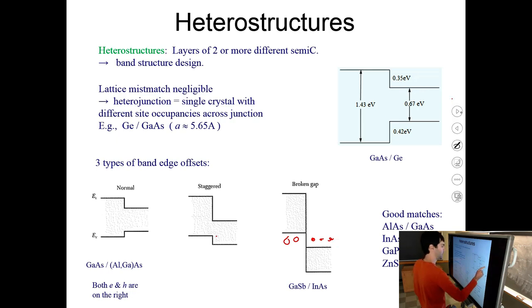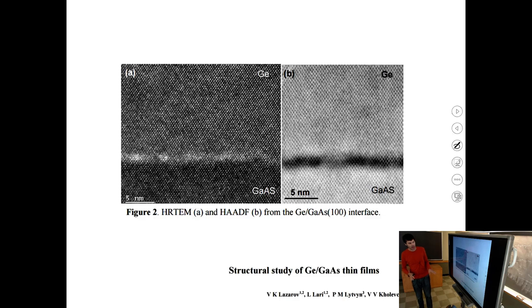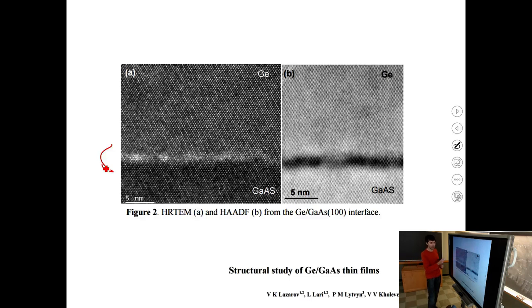Here is an example of a good match combination: gallium arsenide and germanium. This is a high-resolution TEM — transmission electron microscope — image showing the interface. What you can see is atomic rows projected going completely smoothly from gallium arsenide into germanium. This is called an epitaxially grown thin film.